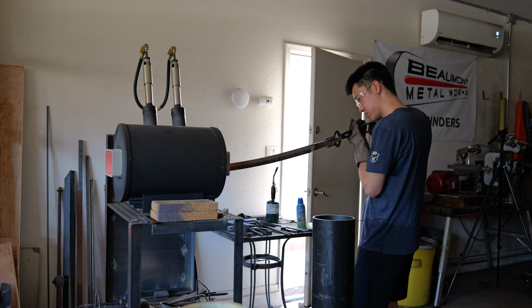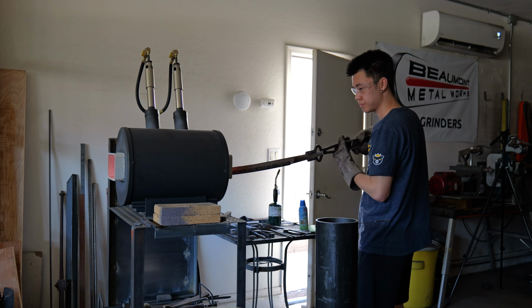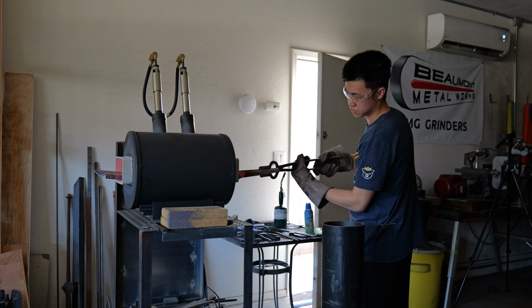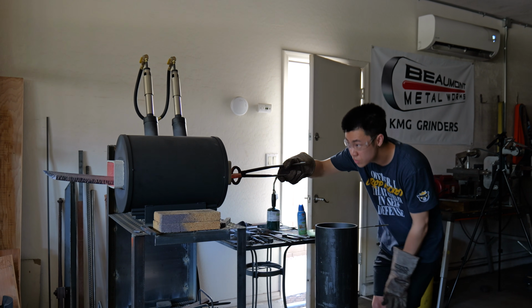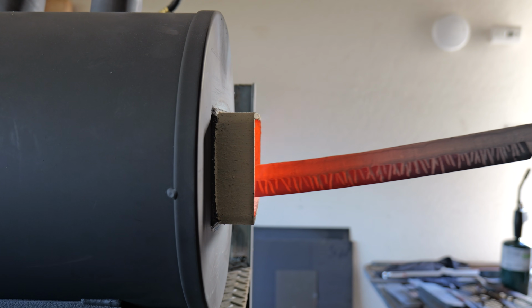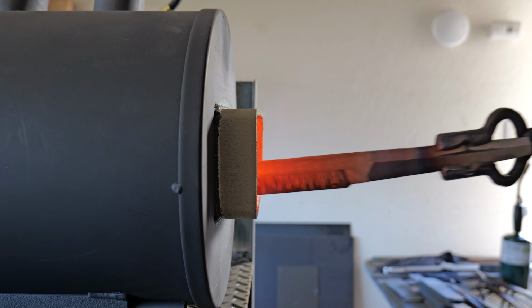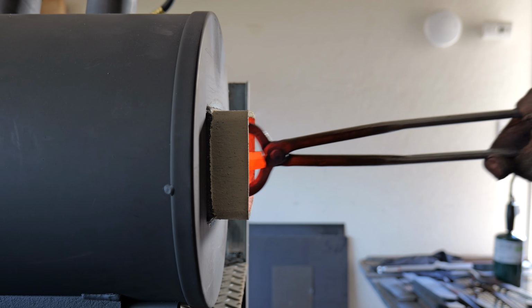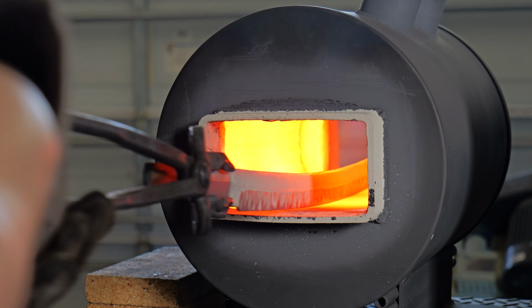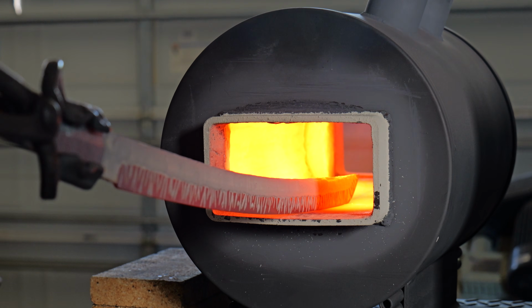I have to be super careful with my temperatures here. If it overheats, the blade could crack. If it's underheated, there'll be no hamon. And if I soak it for too long, the hamon will actually have less activity. That's why I have the garage lights turned off and I have the doors mostly closed. It's probably not great for my lungs, but it'll help produce a better hamon.